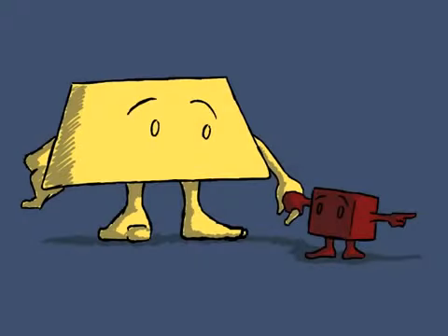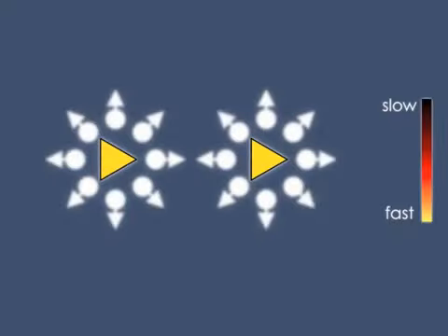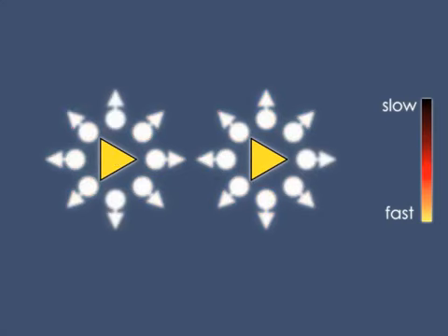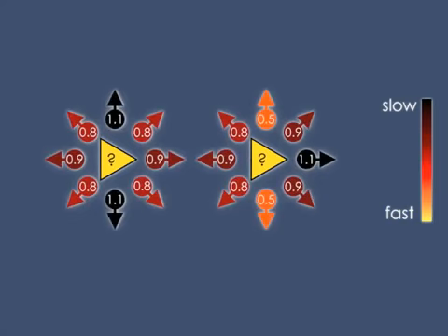To summarize, both theory and experiments suggest that the manipulation characteristics of clusters are indeed governed by the defects they attach to. For manipulation purposes, knowing the types of defects allows you to control the movement of clusters. Vice versa, doing manipulation experiments could allow one to distinguish between different types of defect cluster complexes.